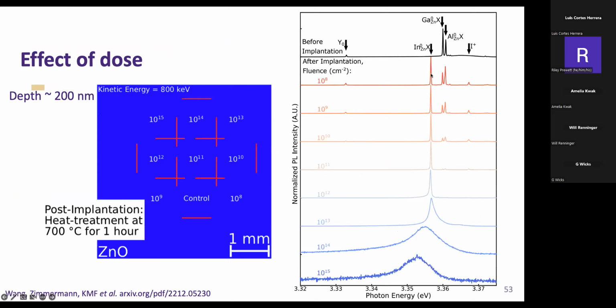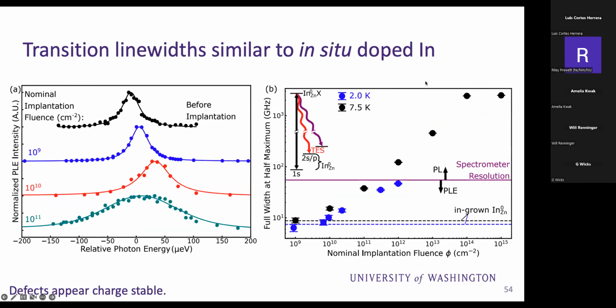This is kind of what it looks like as a function of implantation dose. You do get lines that are as sharp as native indium when you're at the lowest doses here. And very promising. You actually don't know if you have things similar to native indium until you do these photoluminescence excitation, high resolution scans, but you can see at least at 10 to the 9 and below, you have line widths that are comparable or the same as the native indium in the sample. And that's something that's pretty surprising and is not normally observed in systems.